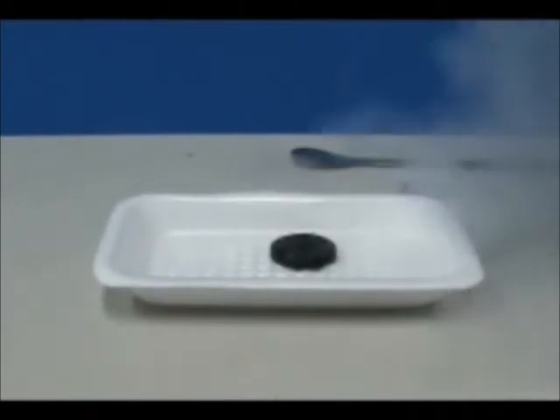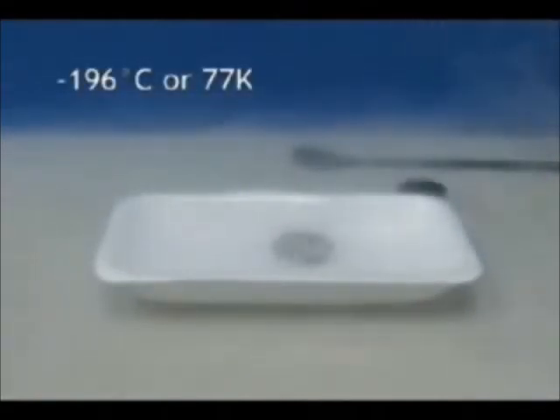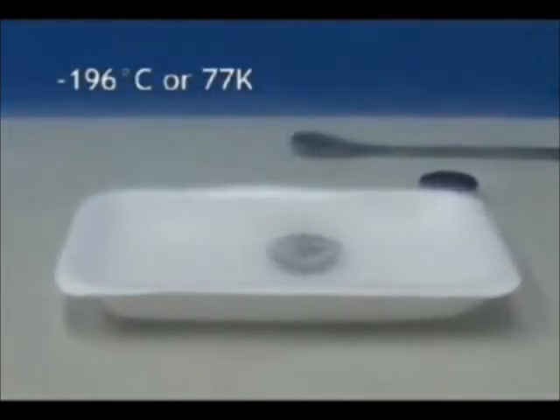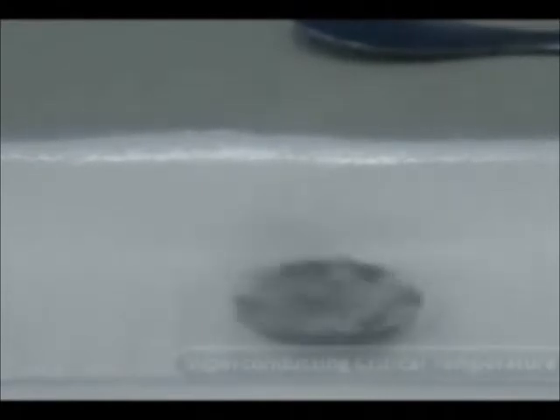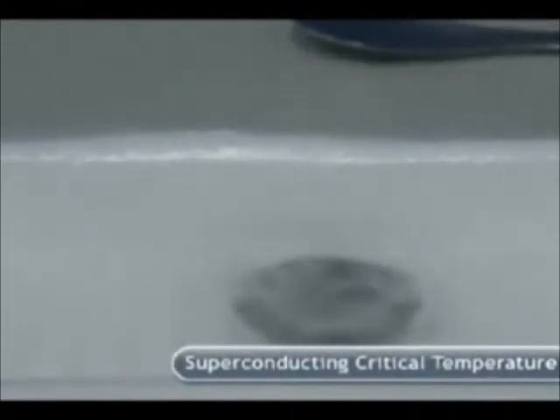The smoking liquid that is being poured onto the superconductor is liquid nitrogen. Its temperature is 196 degrees below zero Celsius, or 77 degrees Kelvin. The liquid near the superconductor undergoes intense boiling due to the heat that the liquid nitrogen absorbs from the superconductor. The liquid nitrogen becomes nitrogen gas, and the temperature of the superconductor drops gradually. When the boiling ceases, it indicates that the superconductor and the liquid nitrogen are in thermal equilibrium. This indicates that the temperature has cooled below the superconducting critical temperature, or 91 degrees Kelvin for the yttrium barium copper oxide compound, and it has established superconducting properties.